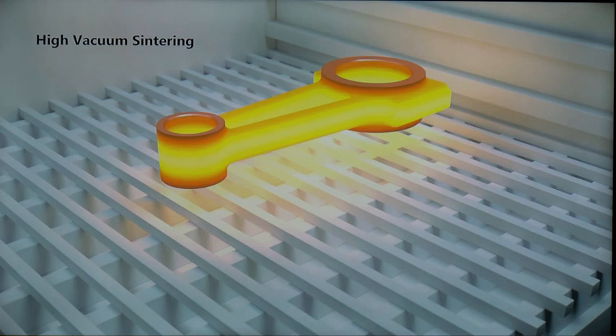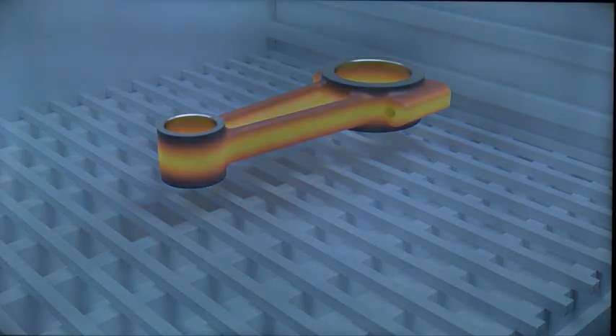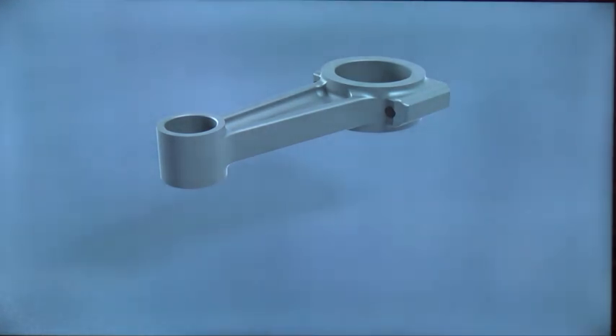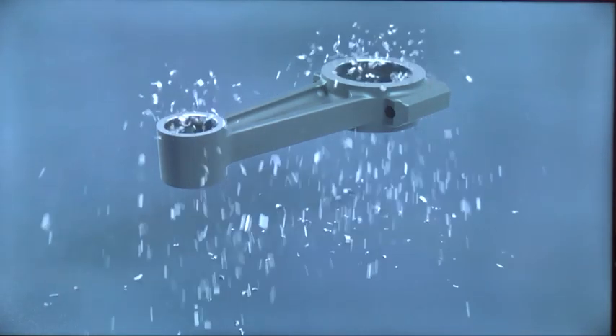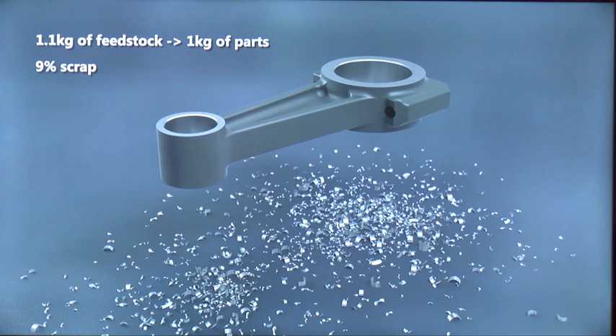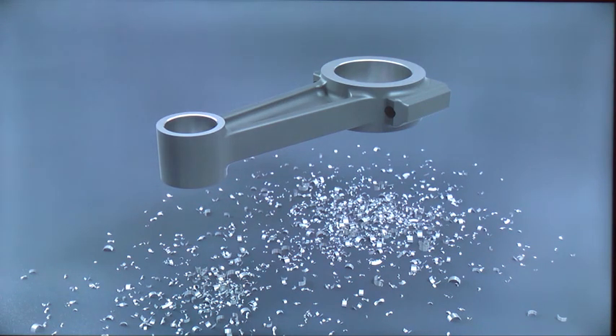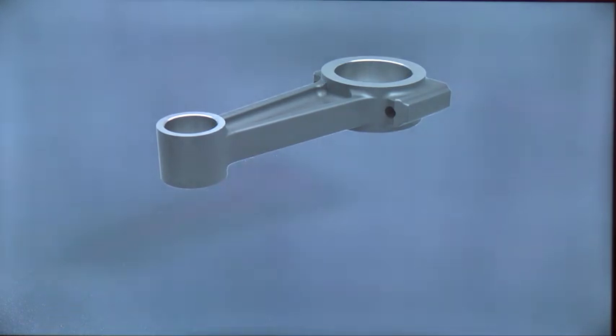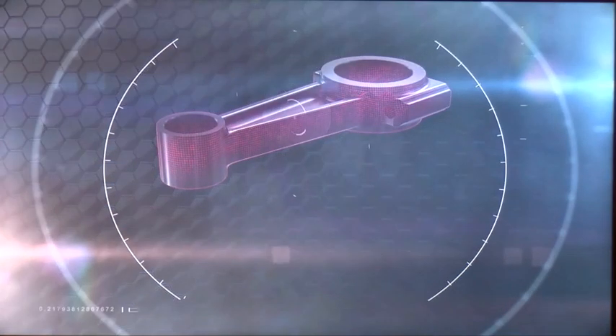So here we put it in an oven and vacuum sinter it. Put it under high vacuum, because titanium reacts with oxygen, and you have an inert gas in there that allows you to heat it up and you get a fully dense material. You have to machine a lot less, so you have 9% scrap compared to 80% scrap, and you can go from 1.1 kilograms of feedstock to 1 kilogram of final parts, for example.